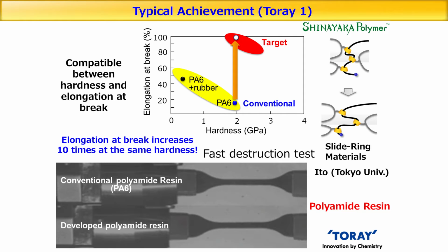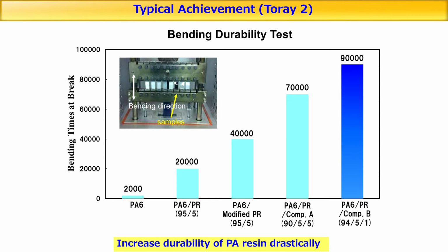What's impressive about this nylon sheet is when we conducted a bending test to see its limits. Ordinary ones would break after 2,000 bends, but with just 5% of the necklace structure added, it withstood 90,000 bends without breaking, indicating a 45-fold improvement in durability. This means it can be used for a much longer time. It's a highly durable polymer, which is crucial for advancing towards a circular economy.